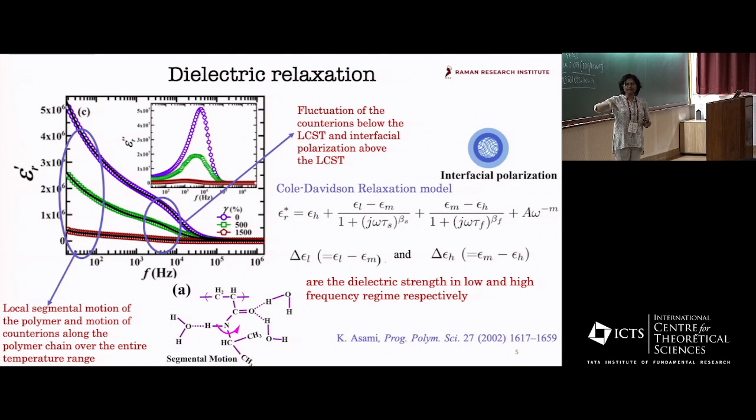And at higher temperatures the particles become very hydrophobic and can form a system spanning gel. But in all the cases, you do see these same relaxations, because, for instance, the slow relaxation comes from segmental motion. The time scales change, but the relaxation is always there. So in most cases we can pick up that relaxation.